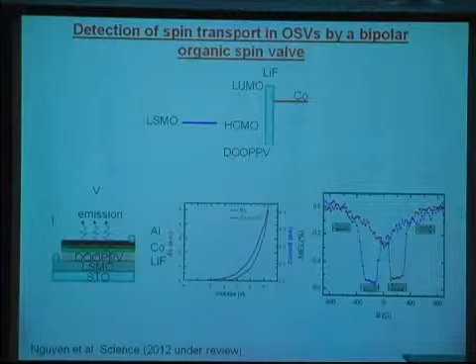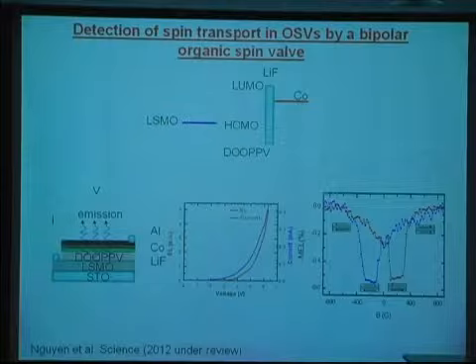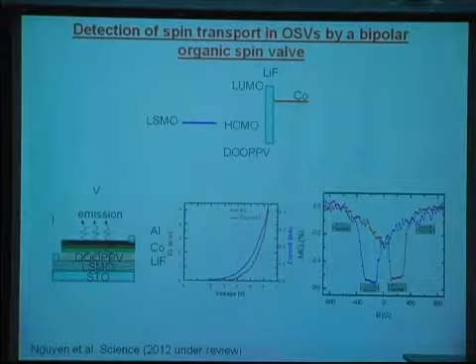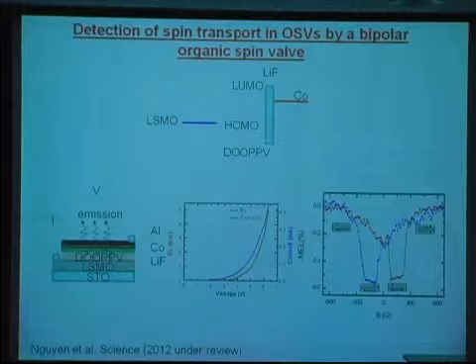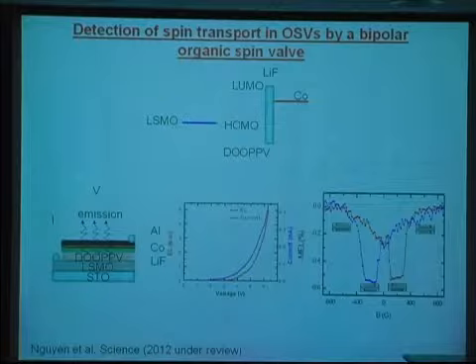Okay. One more question. Yeah. So when this is proof for spin transport, why do Hanle experiments not work? In a Hanle experiment you have a spin that propagates, and now you apply a perpendicular magnetic field, and the spin, as it propagates, starts to precess. Then you would have to see a modulation of your current or photo emission as a function of the applied magnetic field strength.